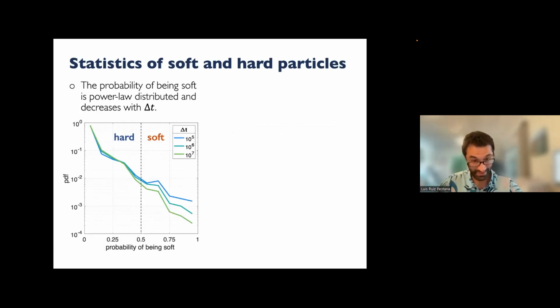Are there a lot of soft particles, a lot of hard particles? So the probability distribution of the probability of being soft is power law distributed. What does that mean? That you have a very high probability that you find a particle in the glass that is hard, okay? Those are probabilities of being soft very low. And then you have a very, very low probability, and again, it's power law distributed, that a particle is soft, okay? What does this mean? That there is a very small minority of particles in the glass that can be considered soft, that actually plastically rearrange when you subject the glass to creep.